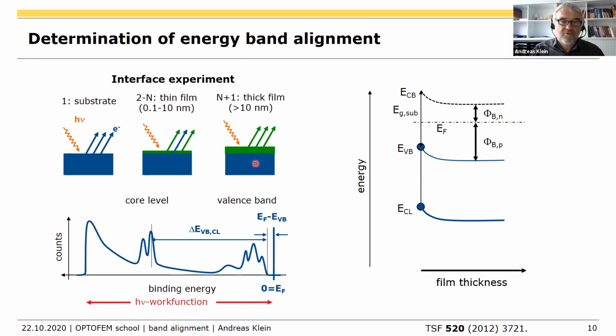But if you deposit a semiconductor on top, you also get the core level of the semiconductor as a function of film thickness, which should ideally show some parallel shifts with the substrate. From the thick film, we know the distance between the core level and the valence band maximum of our deposited film. So that means we can in principle also follow the valence band maximum as a function of film thickness.